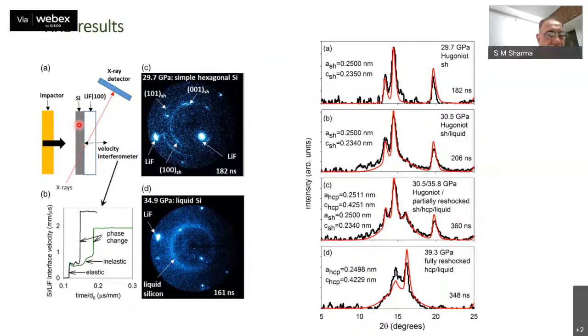So suppose this phase of silicon to begin with was a molten phase, and if we reflected another shock back from the lithium fluoride, it will raise this phase to a higher stress and most likely will transform it to, should I say, a crystalline phase. Is that crystalline phase in any way related to what kind of density you expect at the temperature just before the reshock? The answer we found was yes, indeed.